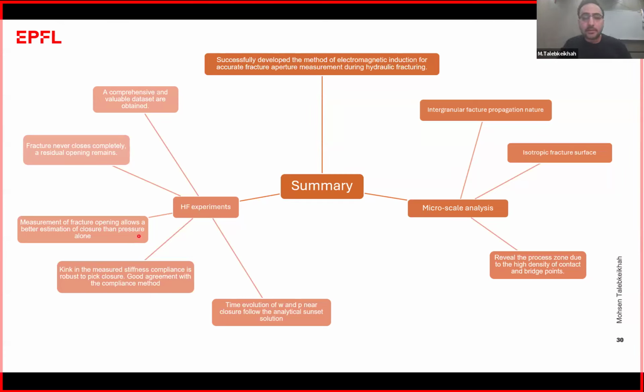And this kink in the measured stiffness value is a robust technique for picking the closure time and pressure. And it is consistent with the compliance method that we had before. And the time evolution of opening and pressure close to the closure follows the analytical sunset solution. And also we showed a strong backstress behavior.